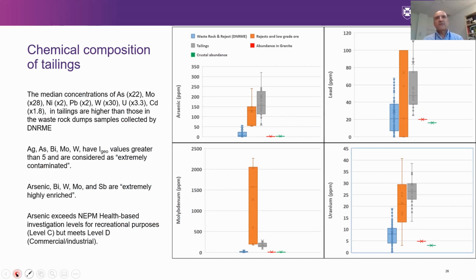Now, the chemistry of tailings shows that they contain high concentrations of arsenic, molybdenum, nickel, lead, tungsten, uranium, cadmium. The median values are higher than the rejects and waste rock dumps and low grade ore. The geo-environmental indexes that we calculated again are high for things like arsenic, bismuth, molybdenum, tungsten.